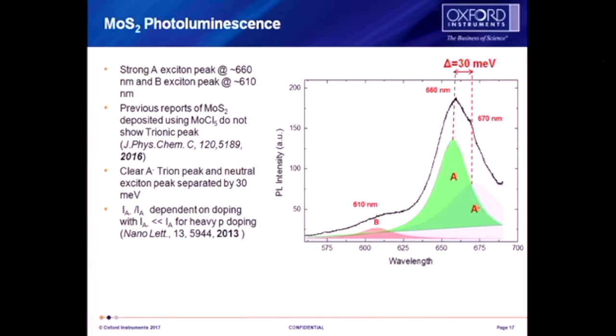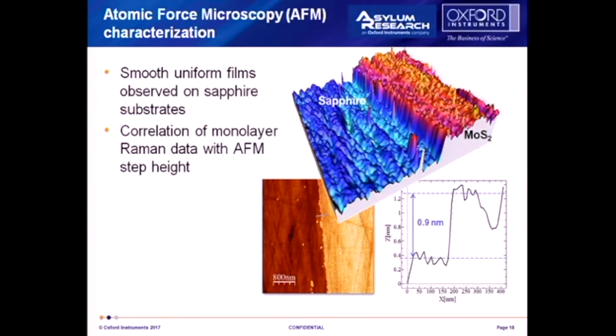But using our Asylum colleagues who are outside, we also checked it to make sure that we could see the step height, that it was 0.9 nanometers, which was measured on an AFM from Asylum, to show that we've got single layer molybdenum disulfide.